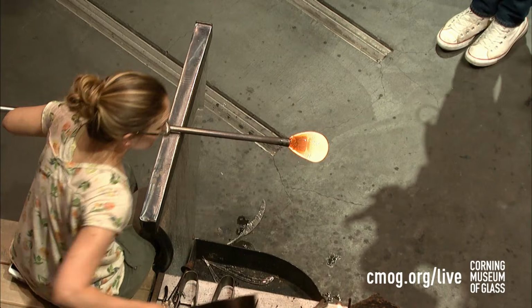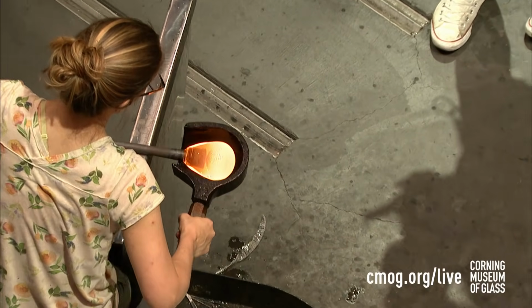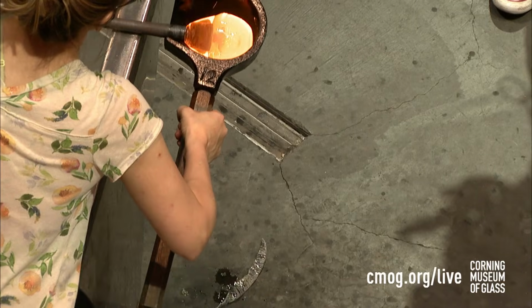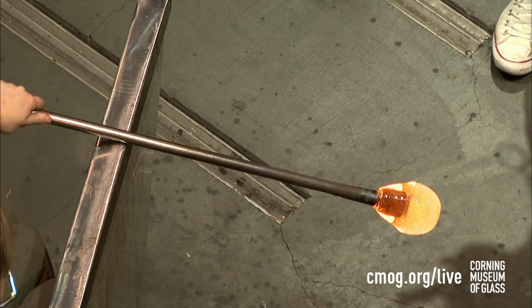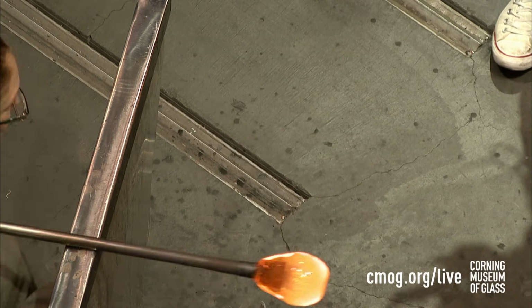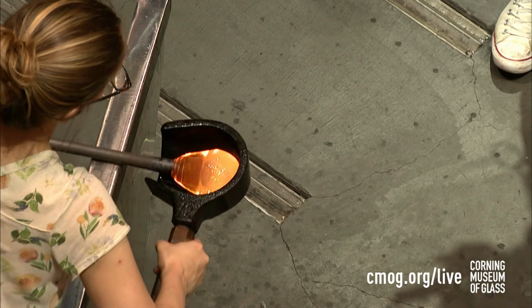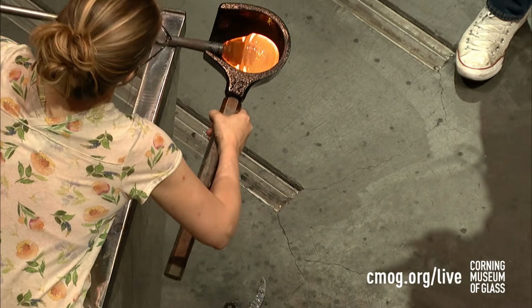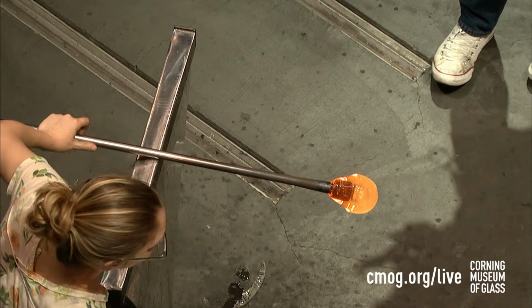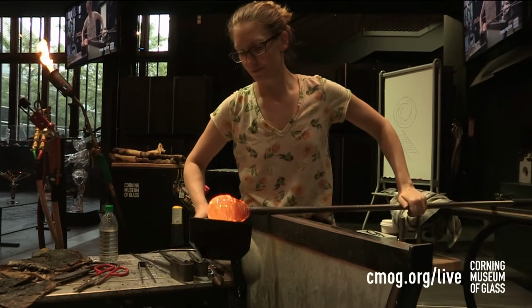If we had it a little cooler, say 1900 degrees or so, the glass would be so viscous, it would be way too hard to turn your pipe once it got inside of the glass. So we figured out 2100 degrees is a perfect temperature to keep this type of glass at, to gather as much as you need, as well as then to sit down at the bench and continue shaping it.